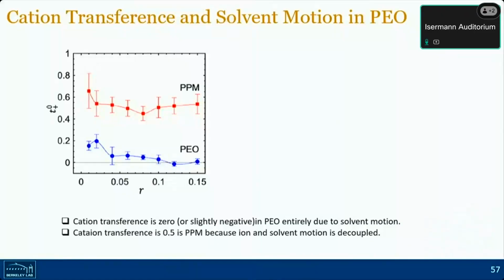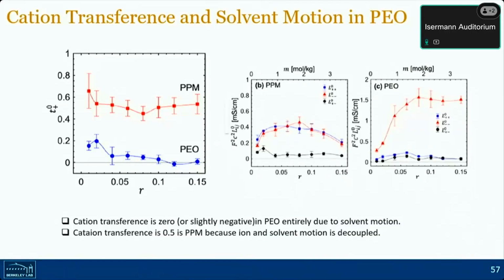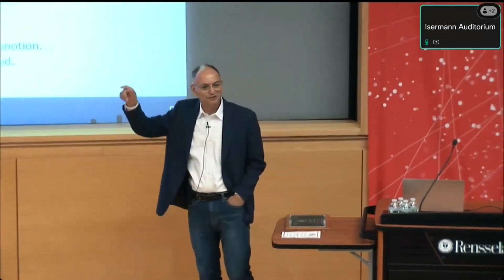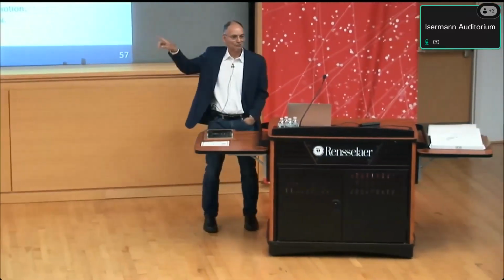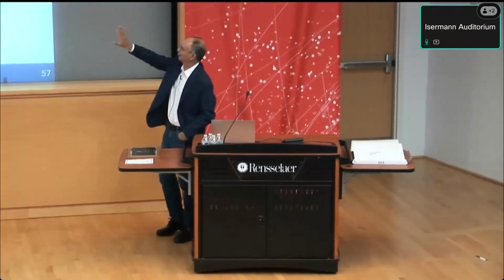And so, in fact, when you do the Onsager analysis, and I don't want to belabor the point, you analyze the quiescent simulations, you see exactly that the transference number of PPM is higher than that of PEO, mainly because the solvent is not being dragged by the cation. The cation solvent correlations are diminished. It's actually not even easy to see it in the Onsager coefficients, because the Onsager coefficients that are relevant are the ion-ion correlations. The solvent is hidden. So you have to go one layer deeper to understand the origin of why these transference numbers are different. You can just see that the correlations are completely different in the 2 polymers.